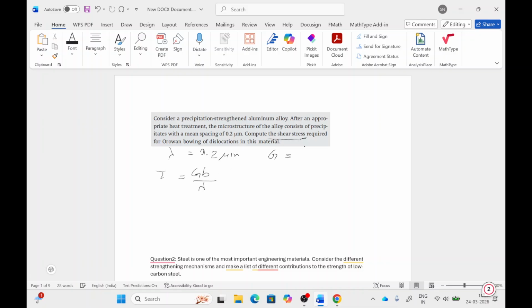The shear modulus for aluminum alloy is 72 GPa, and Burgers vector is generally 0.286 nanometer. When we put these values in, we get G as 72 into 10 raised to power 9 Pascal, into 0.286 into 10 raised to power minus 9, divided by lambda which is 0.2 into 10 raised to power minus 6 meter.